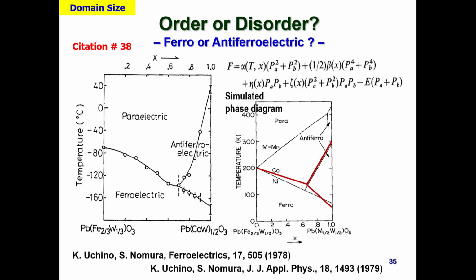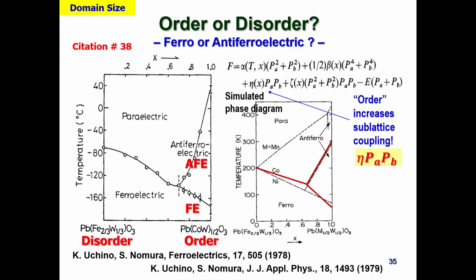So in our 70s papers, the ferroelectric lead iron tungstate and the lead cobalt tungstate, this is 1-to-1 order, this is random. So we can make the gradual change from the random to the ordered structure. So ordered structure is definitely anti-ferroelectric stable. In my papers, they are using phenomenology. Basically what you need to consider is this coupling. Order increases sublattice coupling. In that case, we can make anti-ferroelectric first, and below is a ferroelectric. This is a simulated phase diagram. This is an experimental result. So ferroelectric, anti-ferroelectric, okay?